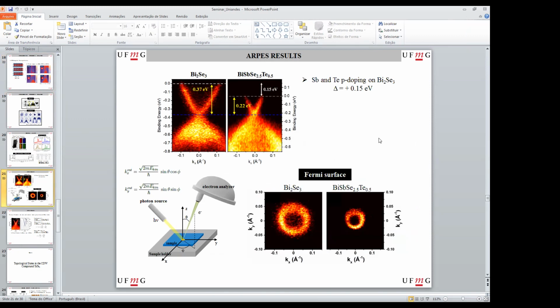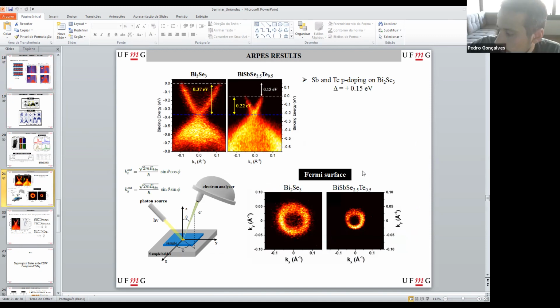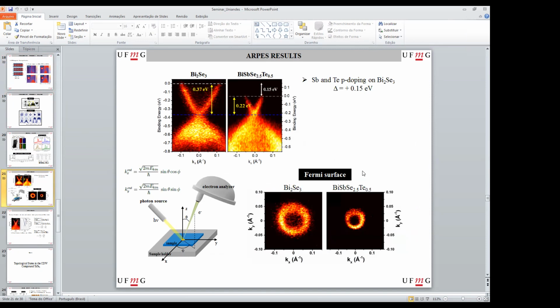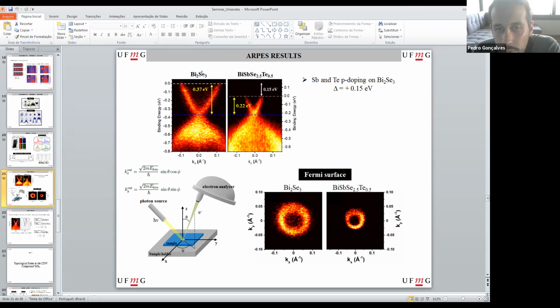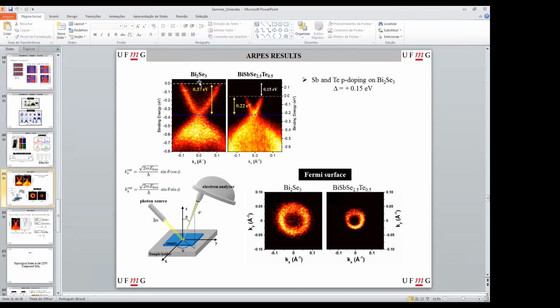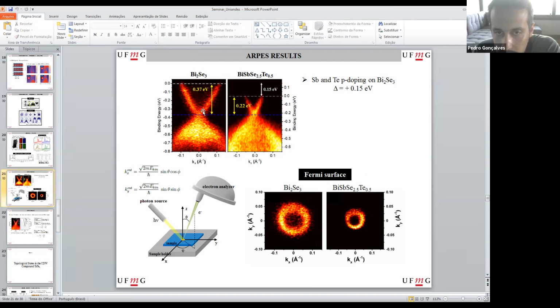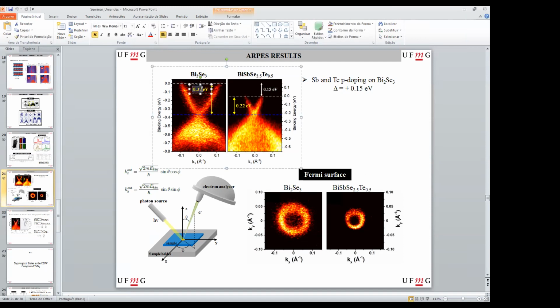That's one. The last question is the following: we know that sometimes this p-type doping comes from the tellurium vacancies, right? Yes. Do you have a kind of metric to say how big this effect of the vacancies is? I mean, how many vacancies do you have in a large unit cell or something like this? The thing is, for bismuth selenide, when we do the calculation, the Dirac energy should be at the Fermi level. It's not at the Fermi level because of the selenium vacancies in the sample. That's the problem in measuring bismuth selenide.